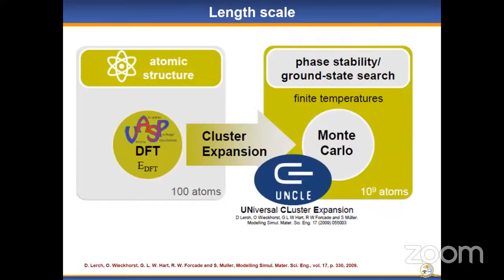Now, this is just an overview of how these are structured. So we have the atomic structure, DFT-based in VASP, cluster expansion there, UNCLE, and then linked to Monte Carlo. So this is quite a repetition of what I have said, but importantly, note that with DFT, you can only do a calculation of a few hundred atoms, while with UNCLE or Monte Carlo here, you can do quite a lot more, with about 10 to the 9 atoms.